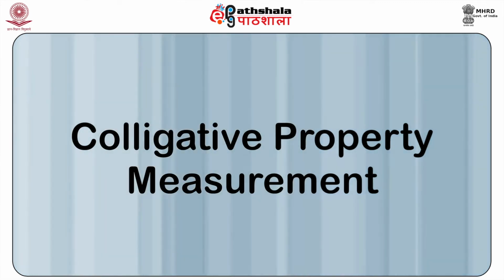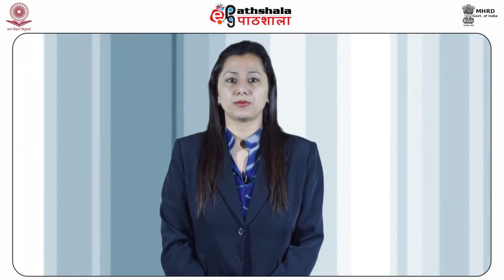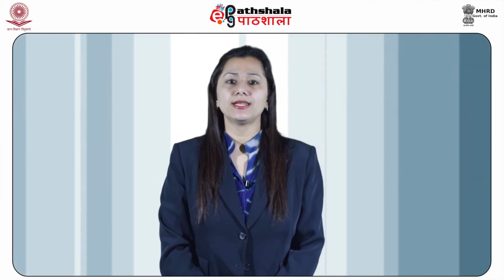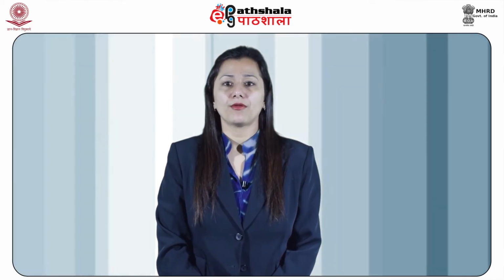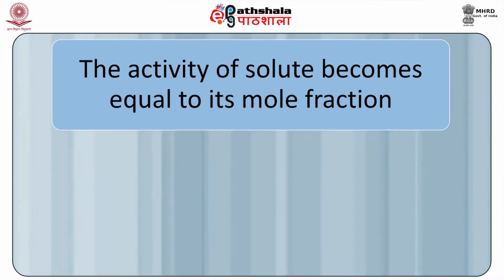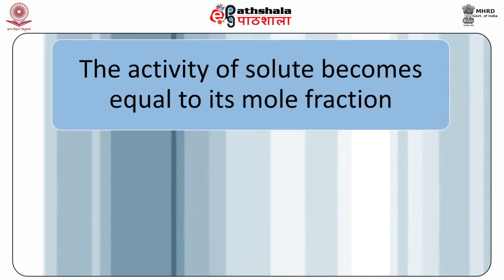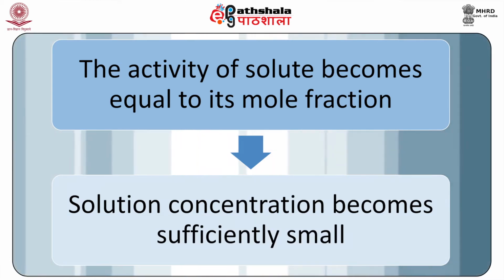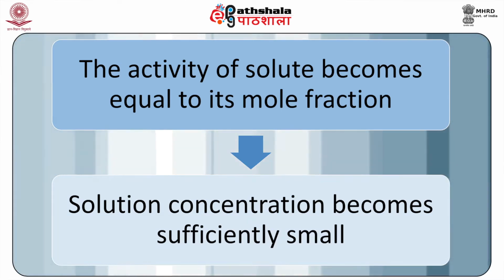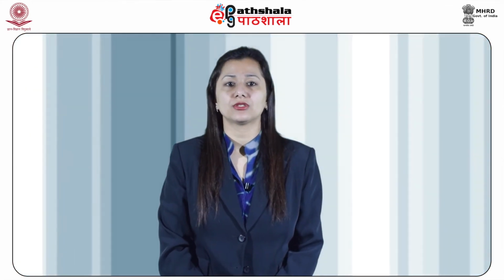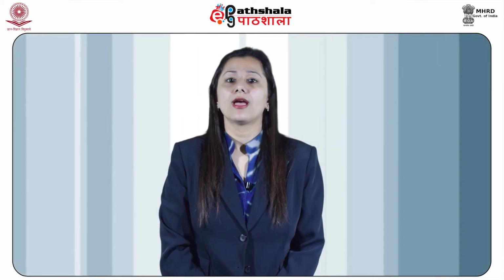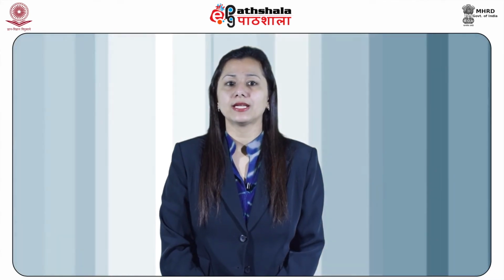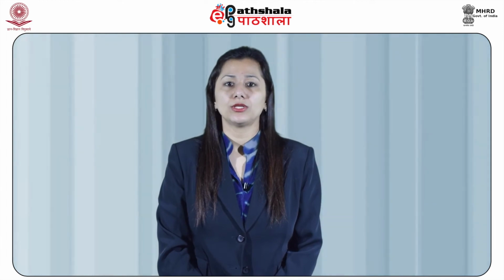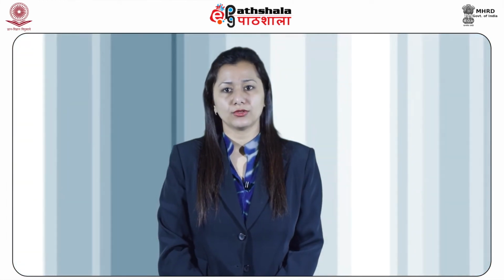Now, we shall have a look at the colligative property measurement. The relations between the colligative properties and molar masses for infinitely dilute solutions rest upon the fact that the activity of the solute becomes equal to its mole fraction as the solution concentration becomes sufficiently small. The activity of the solvent must equal its mole fraction under these conditions, and it follows that the depression of the activity of the solvent by a solute is equal to the mole fraction of the solute.